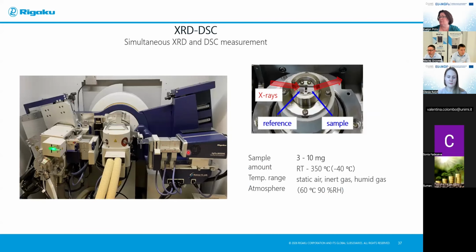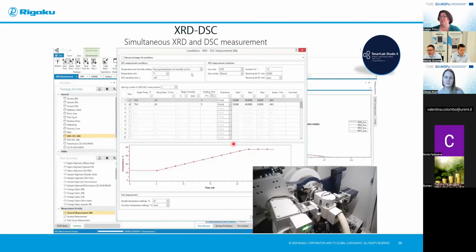The data were collected using the XRD-DSC attachment, which enables simultaneous measurement of XRD and DSC signal, where the sample is mounted on the right-hand side, and here on the left-hand side we have the reference sample. Sample amount is between 3 and 10 milligrams, and we can cool the sample to -40 and heat to a maximum of 350 degrees. We can perform the measurements under air, under inert gas, or humid gas atmosphere. From the software point of view, we have the option to set up measurement conditions by using XRD-DSC measurement, where on the right-hand side, we can specify the conditions for DSC measurement, and on the left-hand side, we can specify the measurement conditions for XRD.